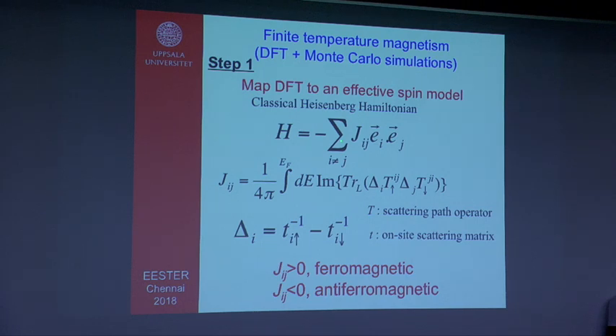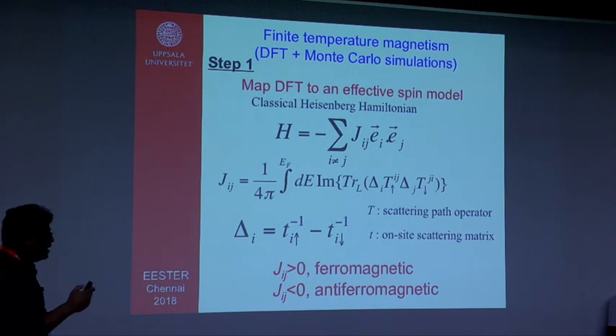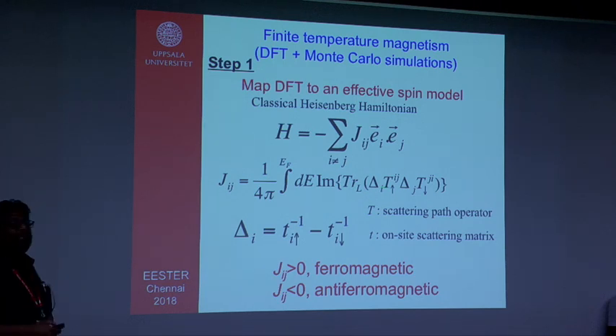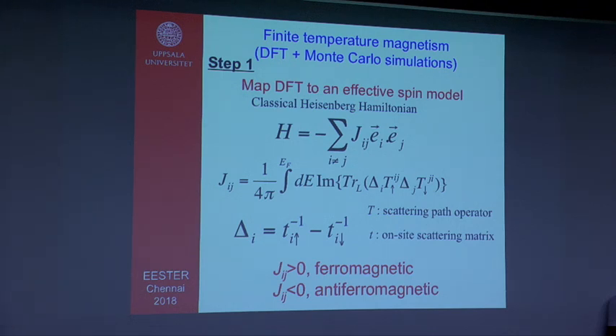Now, there are different ways of calculating Jijs. One of the standard ways is to use a Green's function approach. Manish was talking about the Green's function approach. This calculation of Jij is based on Green's function multiple scattering theory. Let's not go into detail, but you can see an energy integral here, and in its bracket you see the imaginary part of the trace of different quantities. These are related to scattering properties. Electrons scatter from one site to the other, and these are related to spin-dependent scattering properties. That gives you the idea of your exchange interaction between two atomic sites.